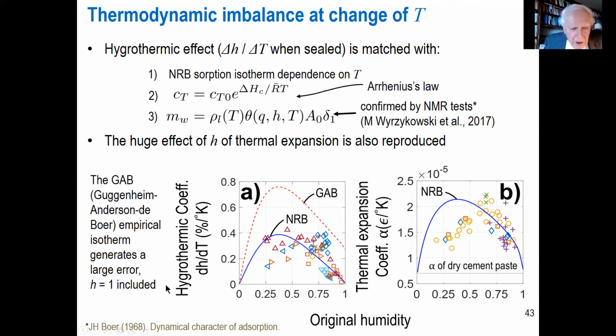And the hygrothermic coefficient can also be modeled. The hygrothermic coefficient means change of humidity due to change of temperature in a sealed specimen. So again, you see that this model fits reasonably well. GAB theory cannot model this. GAB stands for Guggenheim, Anderson, and de Boer.